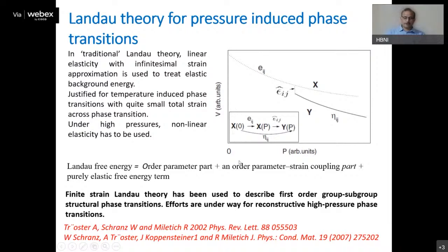Of course, this theory can be applied to the cases where the spontaneous strains are still small, and there is some group-subgroup relationship between the initial and daughter phase. Because in Landau theory, you have to describe the free energy which describes both initial and daughter phase, so there should be some group-subgroup relationship. Of course, there are efforts where people are now trying to describe reconstructive high-pressure phase transitions, where we don't have any group-subgroup relationship. But if you have some pathways, and you know how the atoms are moving in order to go from one phase to the other phase, you can still try to describe the phase transitions in terms of Landau.